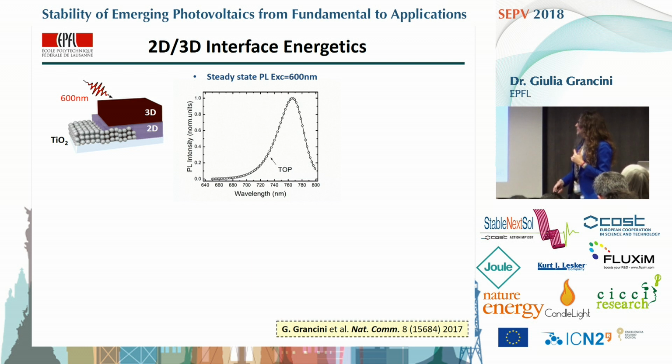But importantly, it's also nice to observe what's going on at the interface between the two-dimensional perovskite and the three-dimensional perovskite. Is it a continuous phase, or what does it happen? And again, simple photoluminescence spectroscopy can give us an answer. In these terms, we excited the material again from the bottom surface and from the top surface, and we explore now the more IR region, more red region, where we see the emission of the standard three-dimensional perovskite.